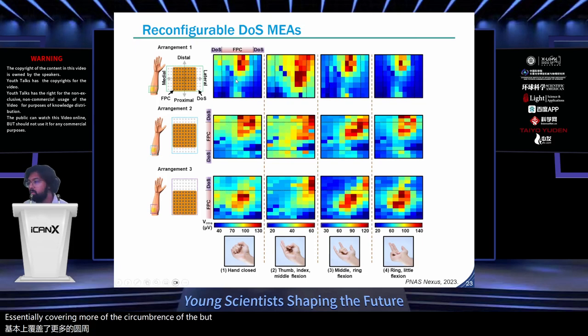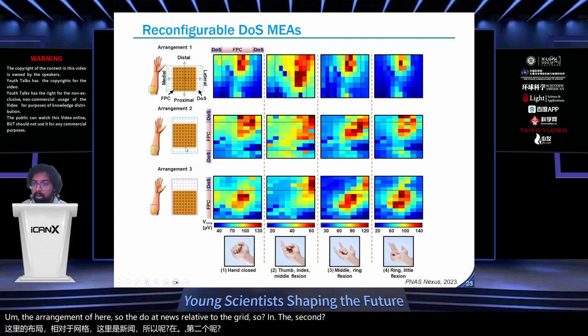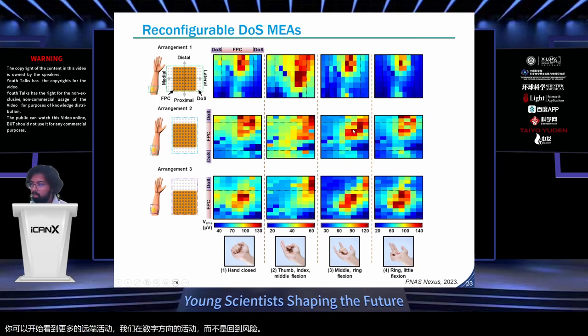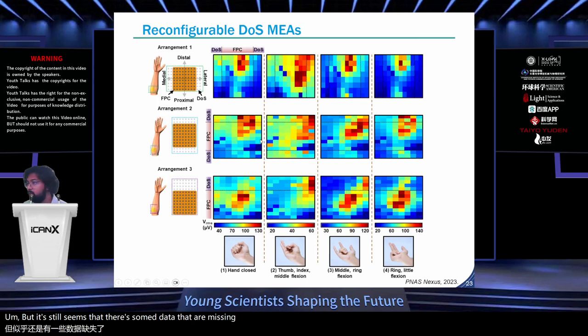But what you can see from these activation maps here for these different gestures, that we miss some activity. Notice that there's more activity kind of going up towards distal down the forearm. So considering this aspect, we decided to reconfigure the DOS MEA relative to the grid. So in the second arrangement, you can start to see a little bit more of that distal activity, or activity in the direction rather, back towards the wrist. But it still seems that there's some data that are missed in all of these maps.